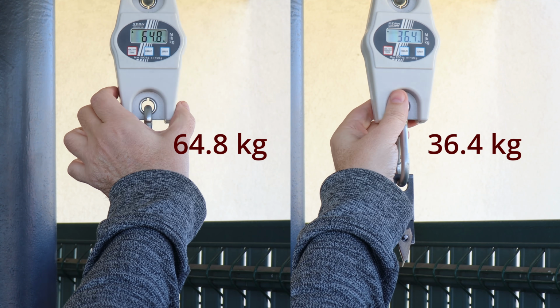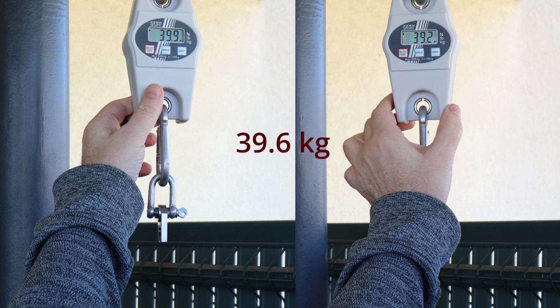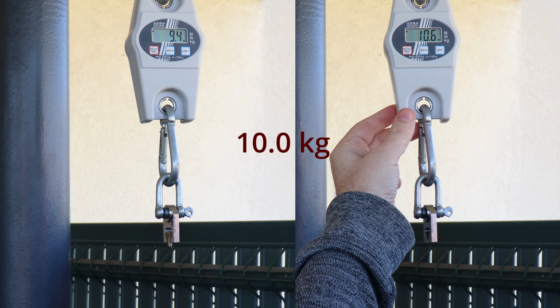Hook test, and the PPA-CF was approximately 1.8 times stronger than the PEEK. The layer adhesion test with vertically printed objects, and this is good layer adhesion, so those modified print settings are good. And let's see the PEEK, and this was quite disappointing.